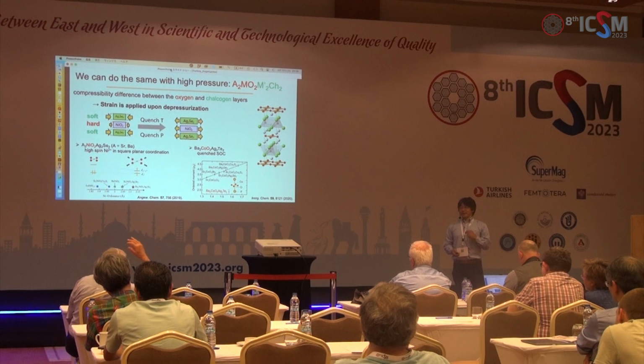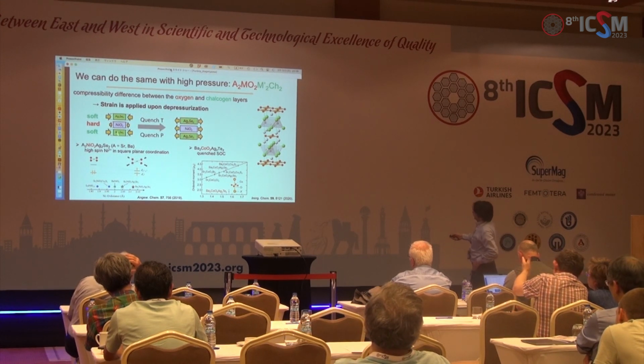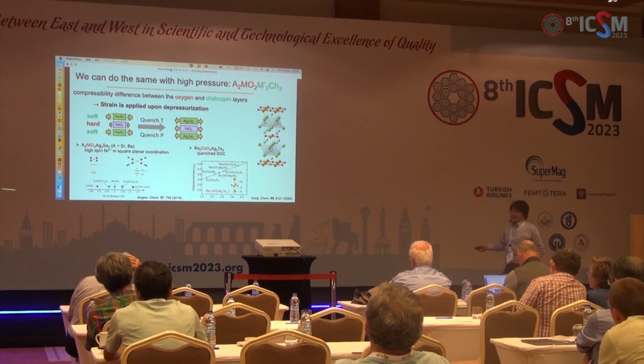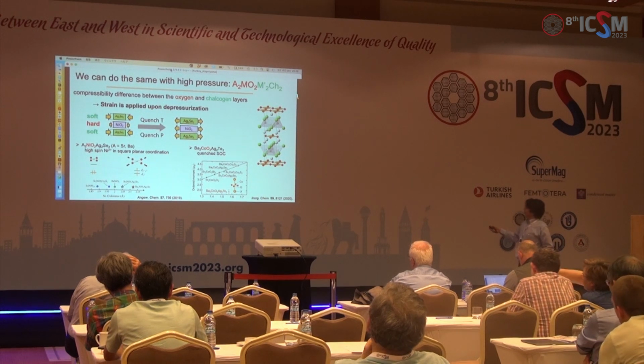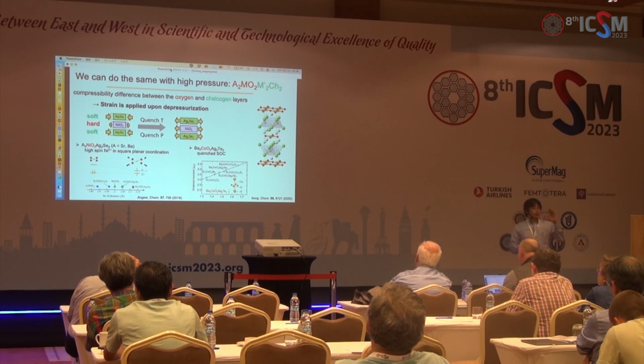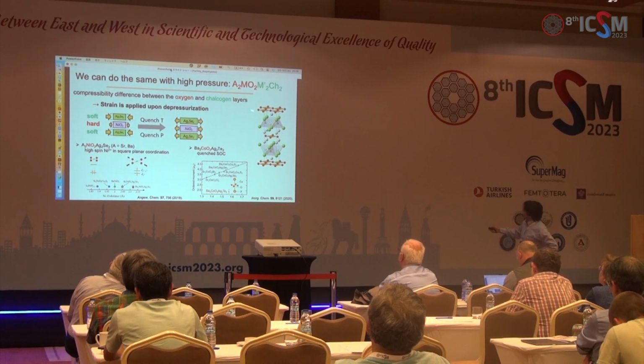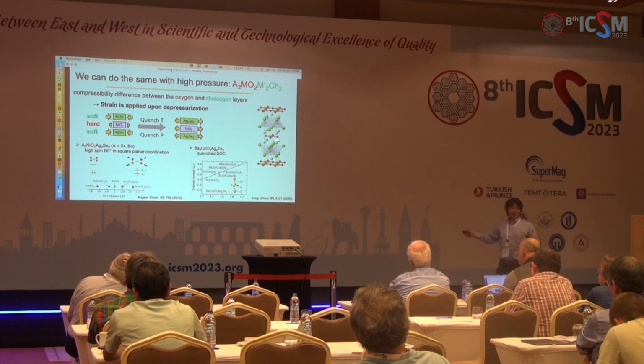But our strategy is different. Recently, we reported several new materials with these compositions. And this is the crystal structure. This structure can be divided into two parts. One is this red one, which is nothing but the oxide layer. And this oxide layer is sandwiched by these chalcogenide layers.